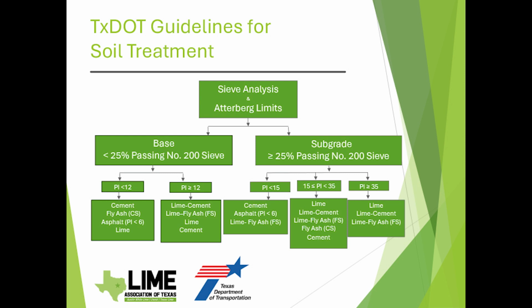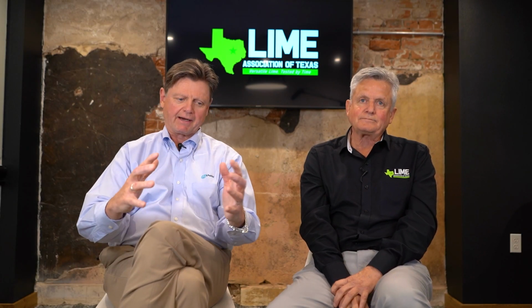As you get a little bit higher on the PI range, the cement actually drops off the chart. So anything above 35 PI is almost always going to be recommended to use lime or some version of lime cement together, or lime fly ash together. And then again, that goes back to just the